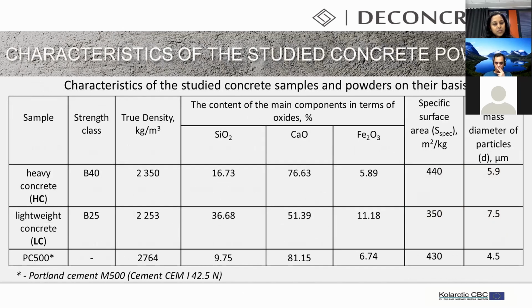Next, we characterize our concrete powders. You can see strength class of original concrete, true density of powders, and the contents of main components in terms of oxides. And as you can see, heavy concrete has more calcium oxides, and lightweight concrete has more silica oxides, because it has mineral insulation materials. And specific surface area after we grind these powders in planetary ball mills is also in this table.